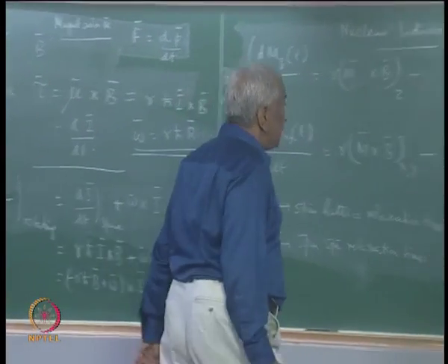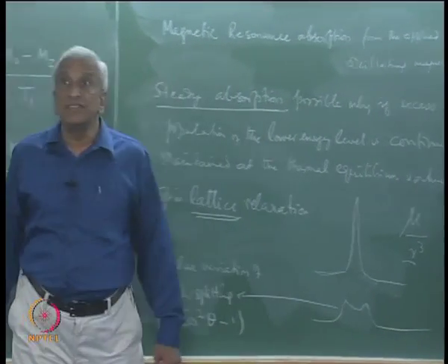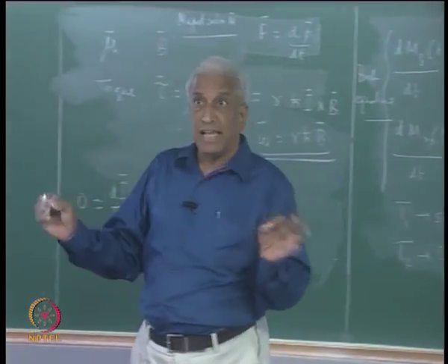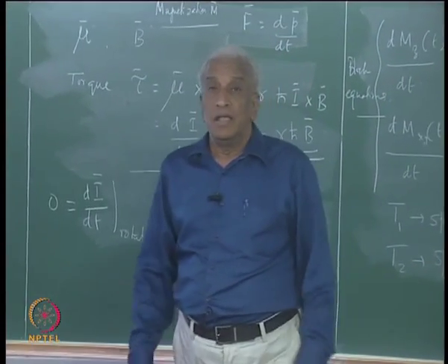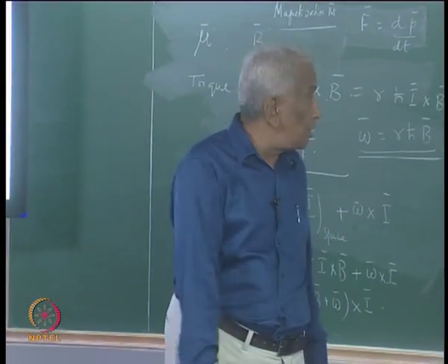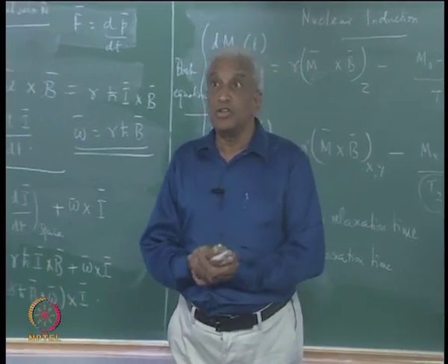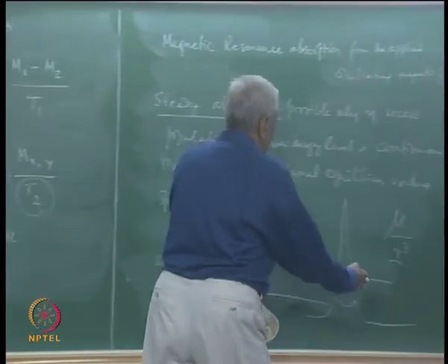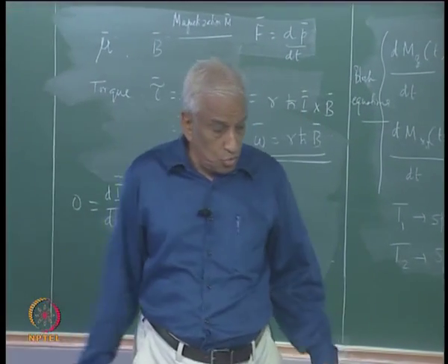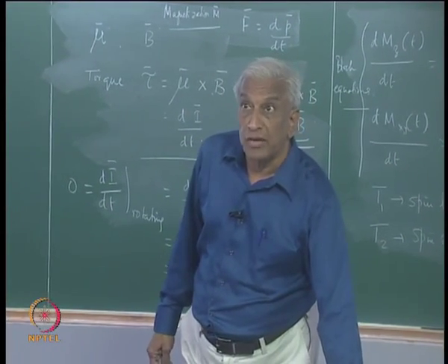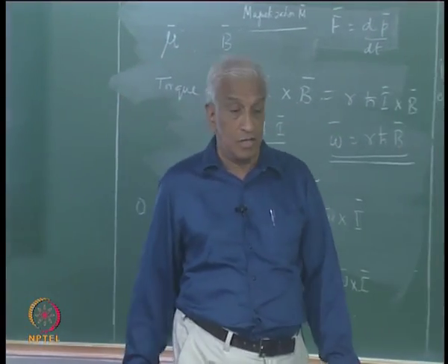Now, this dipolar splitting is determined under the assumption that these spins, the 2 protons, are staying fixed, but at any finite temperature, in a liquid for example, there is a rapid movement of atoms and molecules which causes an averaging out of these local fields, and therefore, the resonance line will be narrowed. This is known as motional narrowing. So, these motional processes also can be studied using such variations.